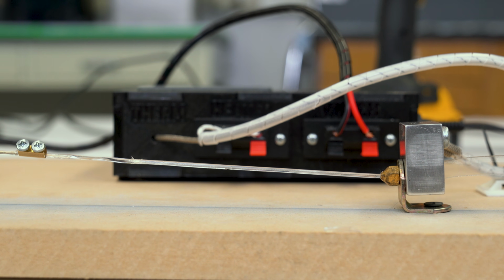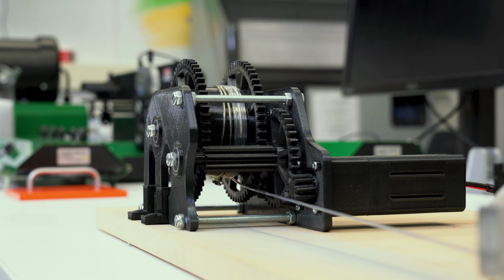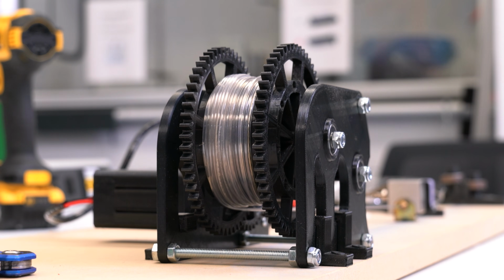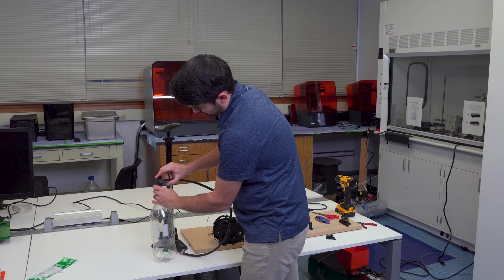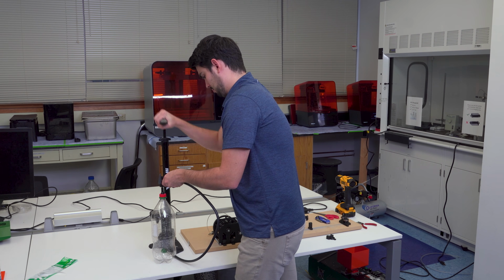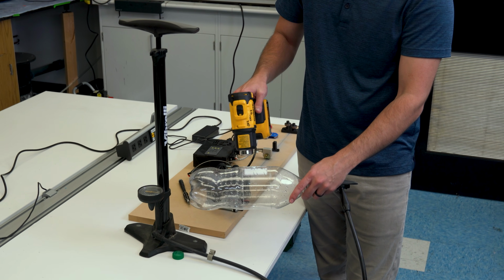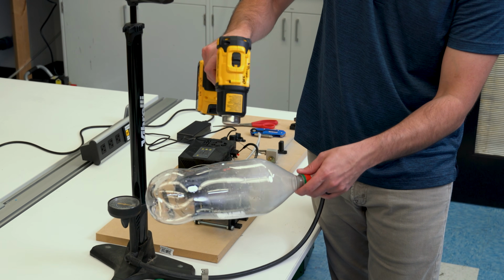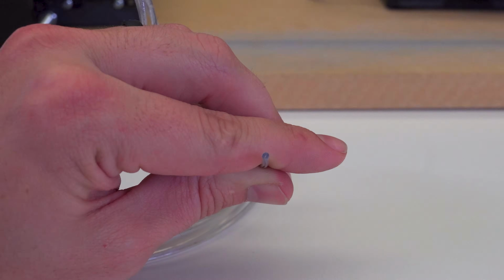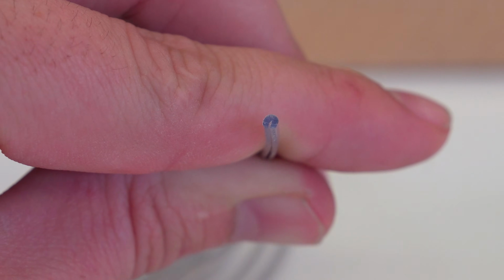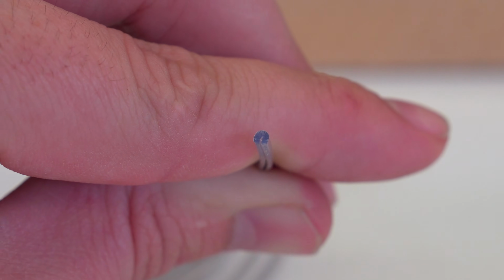And when a 2-liter bottle only contains 50 grams of plastic, it will take 20 hours to make a single spool of filament. This time estimate doesn't include having to remove all the creases out of the bottle by inflating it with a tire pump and then using a hot air gun on it before it can be pulled into a strip. Also, the resultant filament is more of a round tube than a solid fiber, which will cause under-extrusion if used directly on a filament 3D printer.